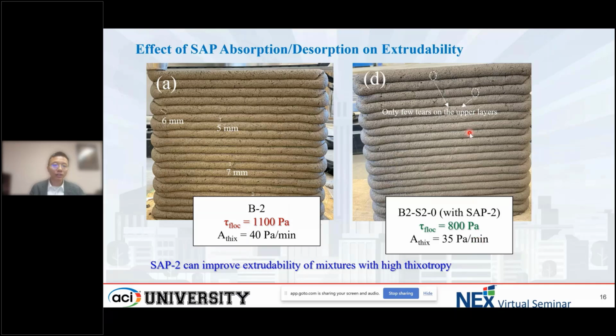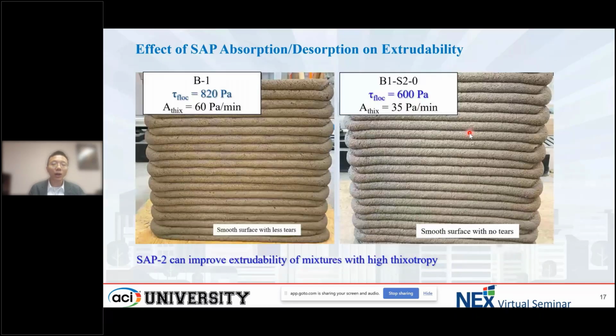And another case is binder 1. Binder 1 has a medium floc value, and so it has a relatively smooth surface. And when we continue to add the SAP2, it has a perfect surface without tears, as the photos show. And in this case, we can make a conclusion that the use of SAP2 can improve the printability of mixture with high or medium thixotropy.